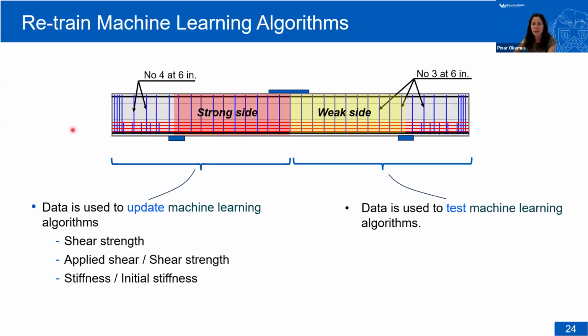One issue we have with this is that the shear strength, we didn't test the strong side, so we don't know the shear strength of the strong side. So we complemented the test data with data we get from finite element analysis. We calibrated that finite element analysis first using the weak side data, and then predicted the strong side, added it to our database.